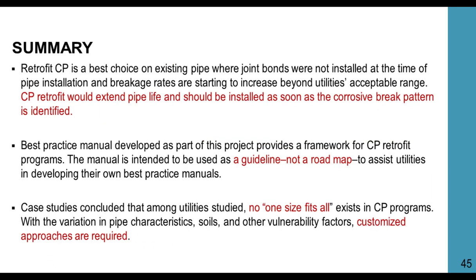Retrofit cathodic protection is the best choice on existing pipe where the joint bonds were not installed at the time of pipe installation, and breakage rates are starting to increase beyond the utility's accepted range. CP retrofit would extend the life and should be installed as soon as the corrosive break patterns are identified. The best practice manual developed as part of this project provides a framework for a CP retrofit program.